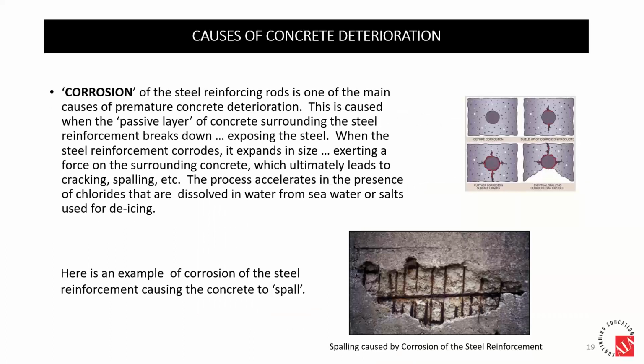Corrosion of the steel reinforcement, or rust, is the cause of spalling. And you see the pictures in the upper right. The first picture is healthy rebar. As that rebar begins to rust, it actually swells in size and it has nowhere to go. So it starts to crack the concrete from the inside out, and that is what we know as spalling. And that picture in the bottom is an example of spalled concrete. You've probably seen this before. Now that rebar is completely rusted and exposed to the weather, that deterioration is going to accelerate several times over.